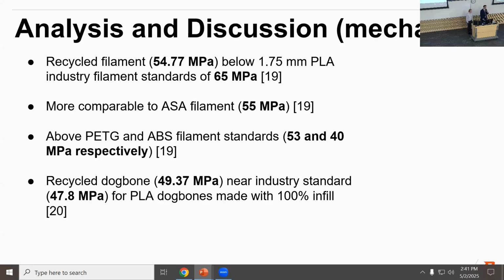When we actually look at a piece that we printed, like the dog bone, we found that our 49 megapascal value is right within industry standards of 48 megapascals for other PLA dog bones that are also made with 100% infill grid patterns.